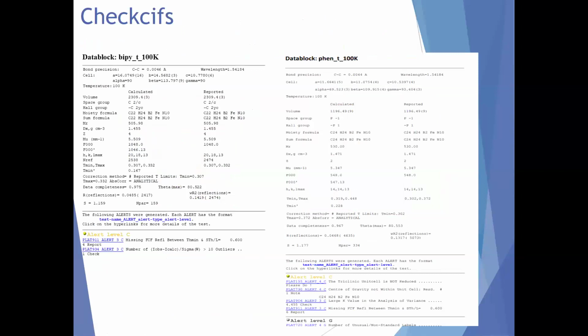Before concluding, here are the two CheckCIFs of two structures. One is monoclinic, the other one is the triclinic one. So the data of these structures were recorded under high pressure on the Synergy laboratory diffractometer. We can see the good quality of the data, very few alerts, only C-type alerts, and no concern for completeness, although the systems are low symmetry. So we can say, to conclude, that the opening angle of the DAC, 120 degrees, associated with the fineness of the X-ray beam produced by a microfocus tube, and the very good quality of the detector, the HyPix detector, help a lot to get such good results.